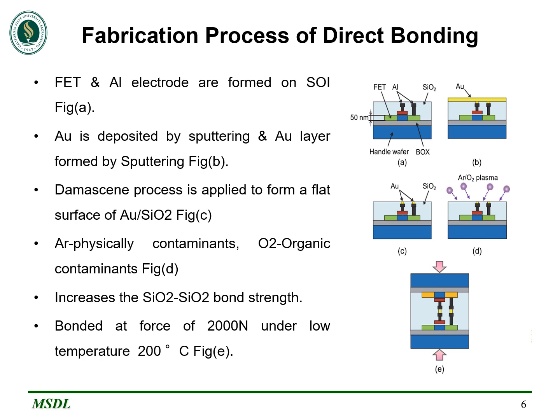The two chips are aligned using an infrared microscope and directly bonded at a force of 2000 Newton for 60 minutes under a low temperature of 200 degrees Celsius, as in figure E.